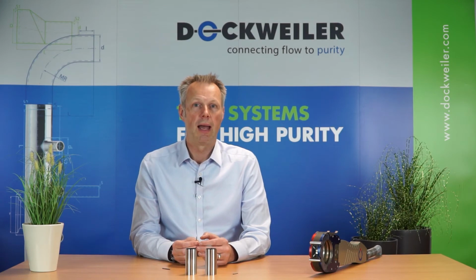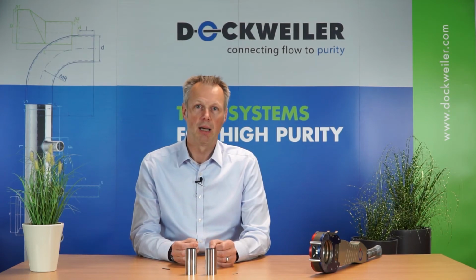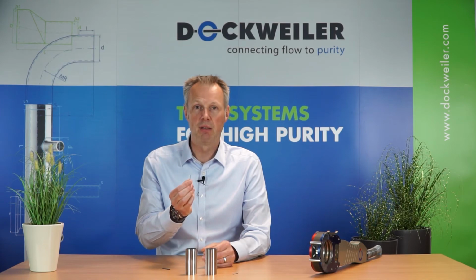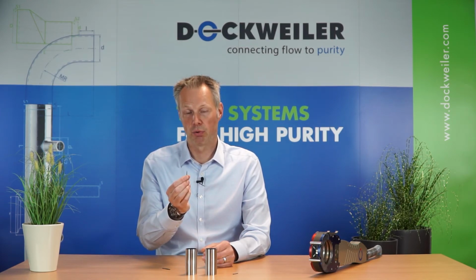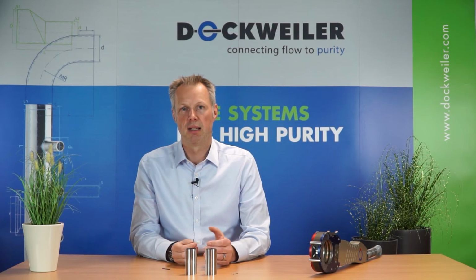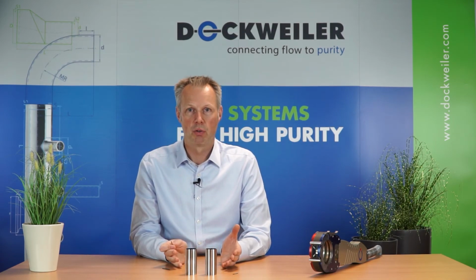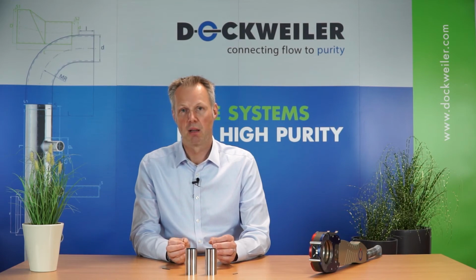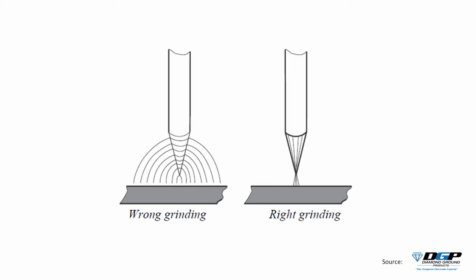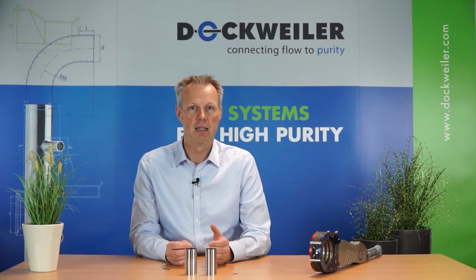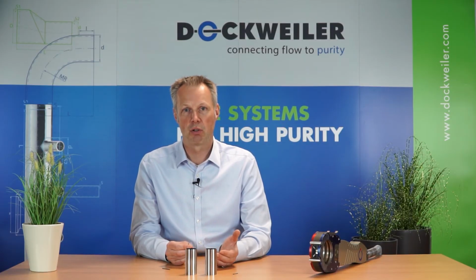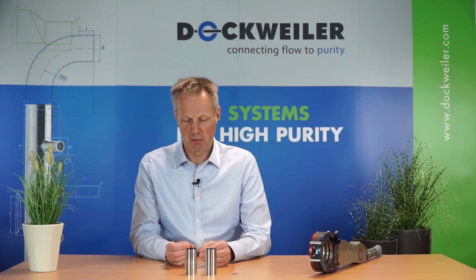then you have circumferential grinding pattern around the tip of the electrode. This is causing, let's say, a lot of different peaks and a lot of different electromagnetic field lines touching or being in contact with your actual tube sample. So again, also here, the arc that you will create is very unstructured and not in line with your purpose.